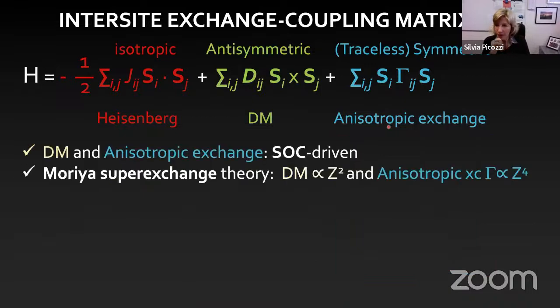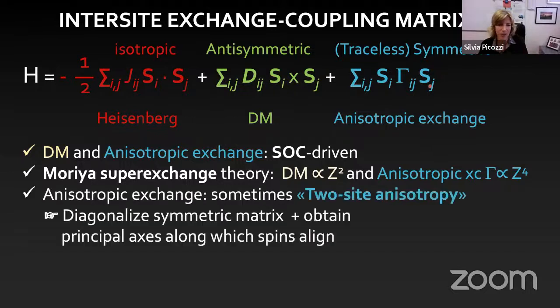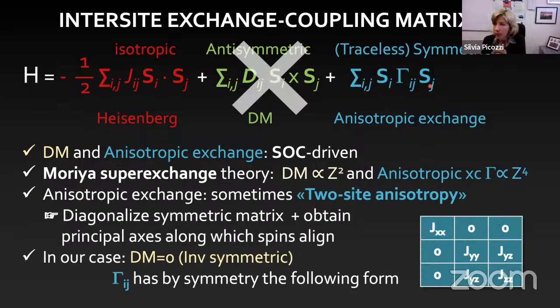Yeah, so in our case, Dzyaloshinskii-Moriya and anisotropic exchange are both related to spin-orbit coupling, which means that we expect large effects on heavy atoms and small effects on light atoms. From the symmetry point of view, it is known that if I have inversion symmetry in my system, I don't have Dzyaloshinskii-Moriya. So Dzyaloshinskii-Moriya is only there when I break inversion symmetry. And in my nickel halide, I do have inversion symmetry, which means that I don't expect any DM interaction here.